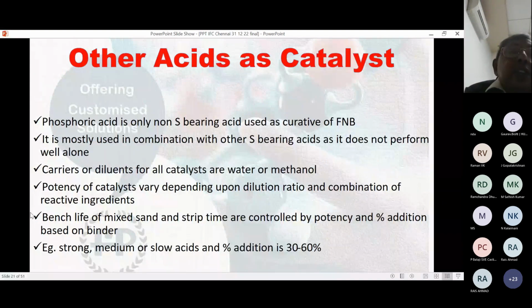So, other acids as catalyst. Phosphoric acid is the only non-sulfur-bearing acid used as curative for furan. It is mostly used in combination with sulfur-bearing acids as it does not perform well alone. Carriers or diluents for all catalysts are water or methanol. Potency of catalyst varies depending upon dilution ratio. That means if you take the example of paratoluene sulfonic acid, if you dilute it to 70%, 60%, 50%, the more it is diluted, the less is your reactivity, or it increases bench life.